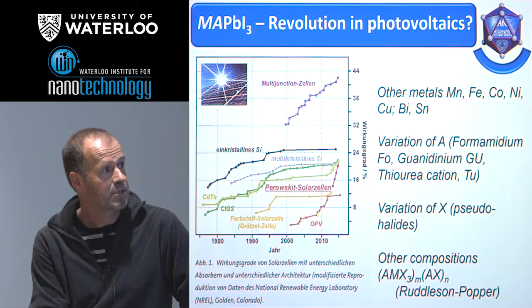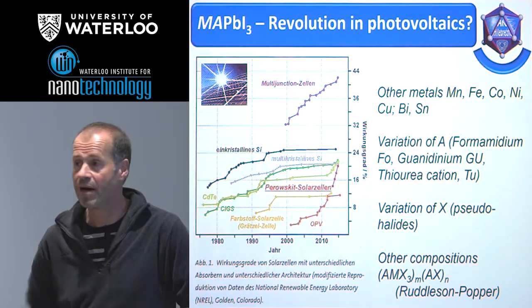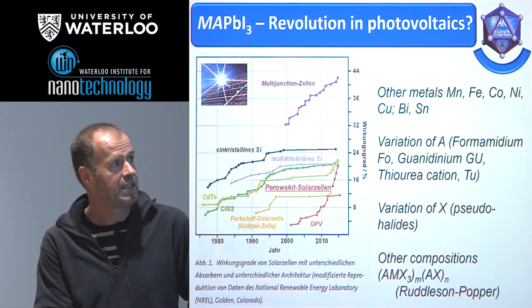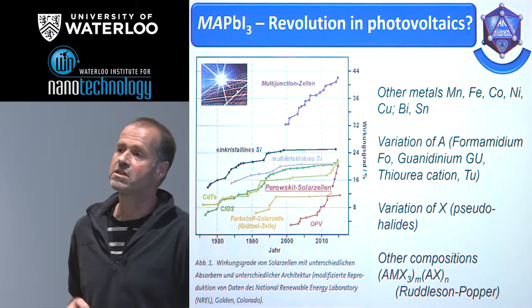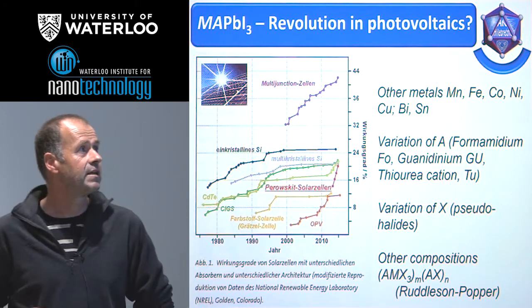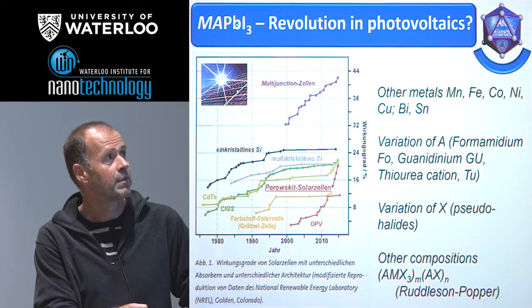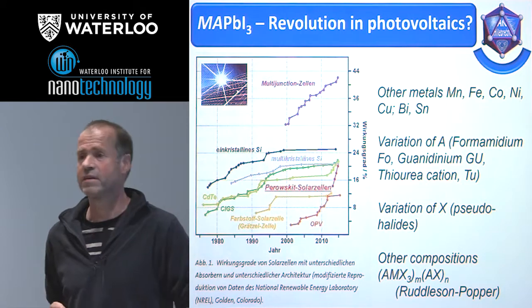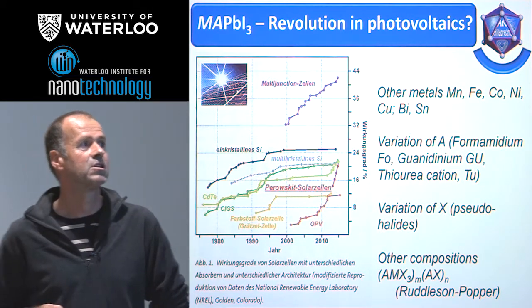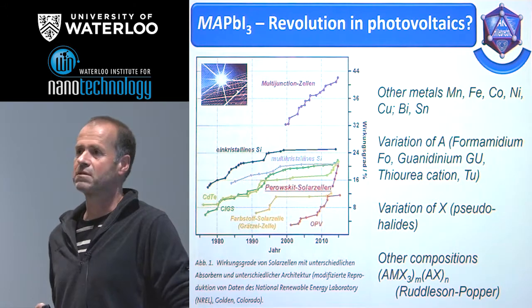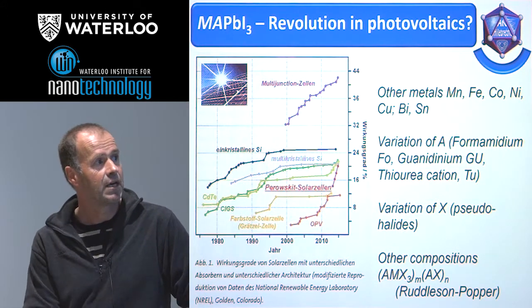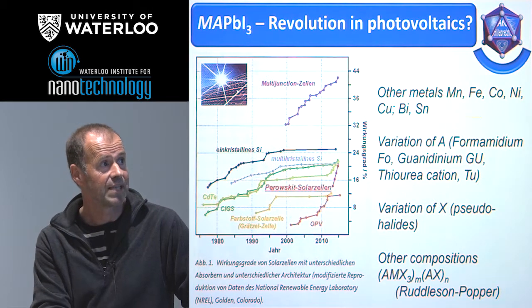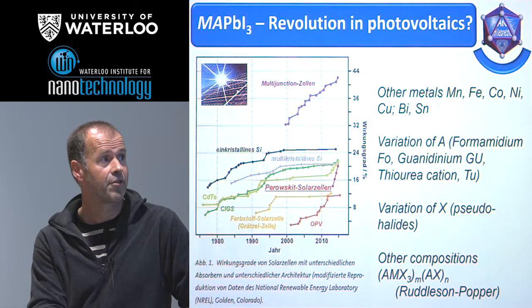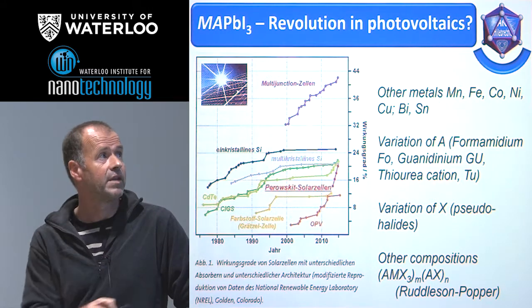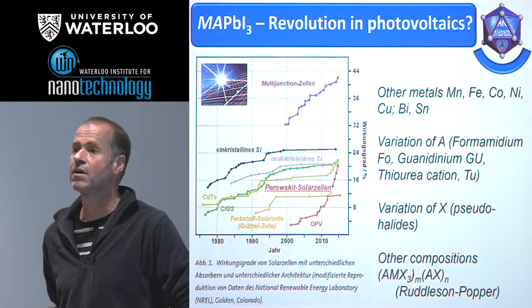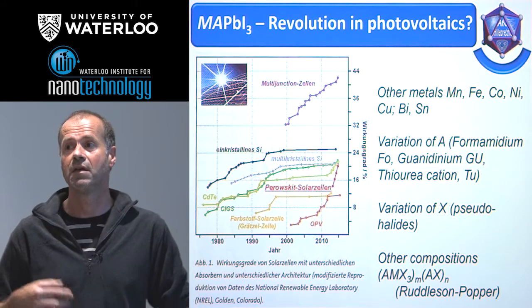During a few years, it was possible to increase the efficiency to a value above 20% if you compare the time which was needed to do it with other materials for the solar cell. You see the tremendous development. Now the idea is, this is methyl ammonium lead iodide. This is the so-called perovskite structure. So this is the perovskite solar cell. And it looks good, but lead is not the best metal you can use. So part of the investigations is the substitution of lead by other main group or transition metals, the variation of the organic cation. These are so-called hybrid materials, organic-inorganic materials.